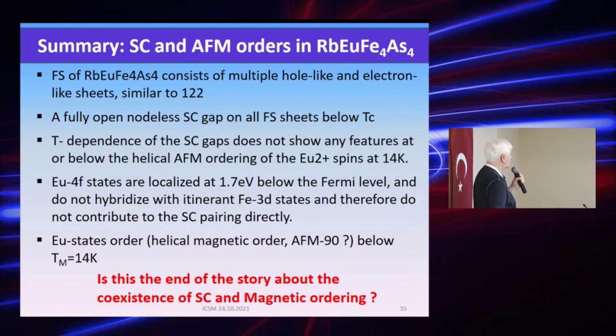Now, we may summarize the result as follows. Clearly, the Fermi surface of this compound consists of multiple hole-like and electron-like sheets, and this is similar to the 122 system, which is well known. The superconducting gap, which is probed by the ARPES technique, by Andreev spectroscopy, and by scanning tunneling microscope, doesn't show any nodes, so we conclude that this is a nodeless superconducting gap, and its temperature dependence is consistent with BCS, so we didn't observe any anomalies.